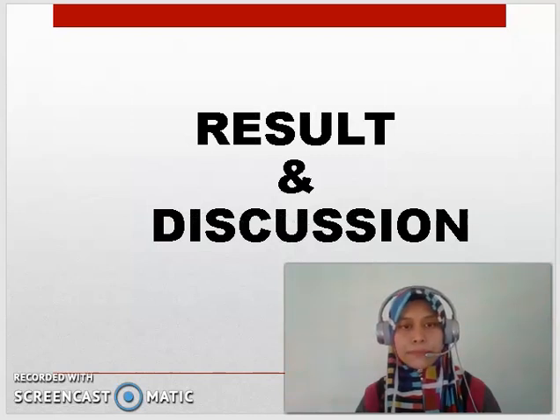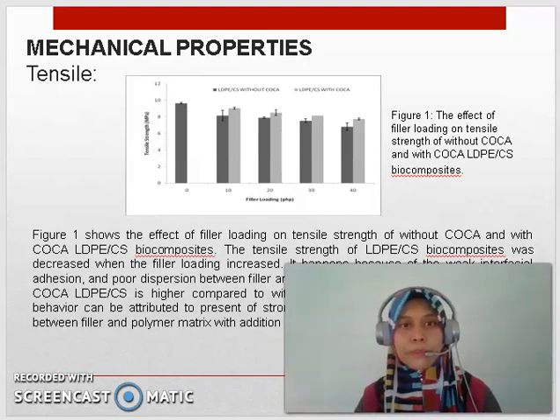Results and discussion. Here we have the mechanical properties. First is about the tensile. Figure 1 shows the effect of filler loading on tensile strength without COCA and with COCA for LDPE or CS biocomposites. The tensile strength of LDPE or CS biocomposites decreased when the filler loading increased. It happens because of the weak interfacial adhesion and poor dispersion between filler and polymer matrix. The tensile strength of LDPE or CS with COCA is higher compared to without COCA biocomposites. This behavior can be attributed to the presence of strong interfacial adhesion and better dispersion between filler and polymer matrix with the addition of COCA.